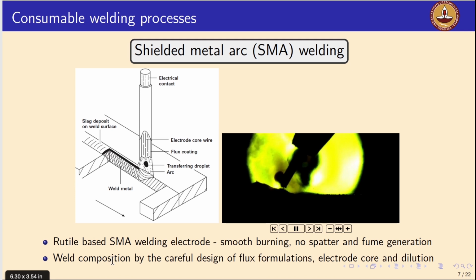So the weld composition is achieved by carefully designing the flux formulation, the electrode core, and the dilution from the base material, right? So now we'll straight away dive into how we can generate an electrode to weld the carbide-free bainite containing high-strength steels.